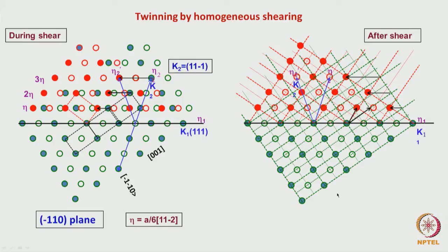These 4 terms are very important in understanding twinning crystallography. That means there are 2 planes which are undistorted. By deformation they do not undergo any transformation, they only undergo a change of orientation. Similarly, two directions are also there.